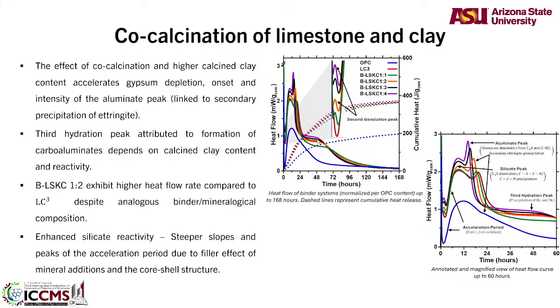That red one, by the way, is LC3. So LC3 still does that because of the calcined clay. But if you add a little more calcium oxide through that additional carbonation, you get this very quick peaks early on. And you have this aluminate and silicate peaks picking up much, much further. That gives you added strength.